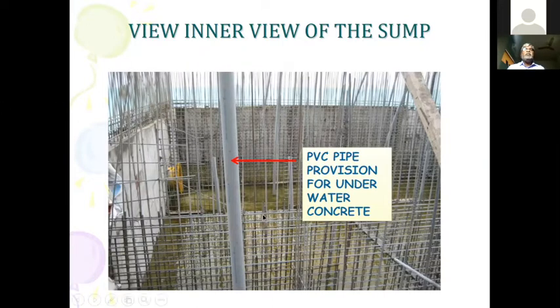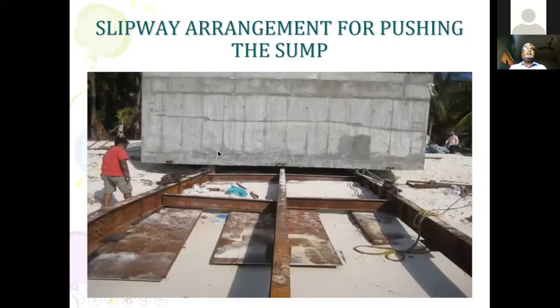So what we did is, when we casted this raft, we provided PVC pipes, about 18 numbers, so that we'll be pouring this non-shrink free flow grout, which sets underwater, after making the barricade underneath the seabed at 9.1 meter, so that this grout does not flow. And as this grout has a non-shrink property, it expands and makes a perfect contact between the bottom of the raft and the seabed.